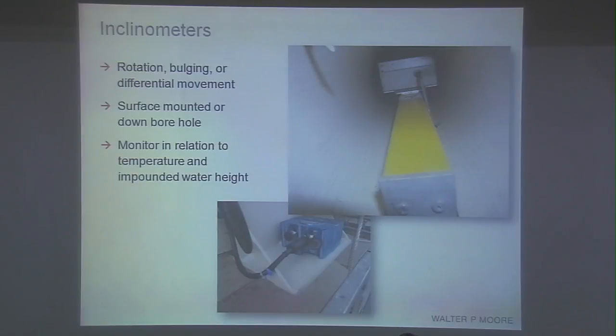Certainly, as some of the other presenters have mentioned, we want to measure all of the known factors which may influence the data, such as temperature and water height, and maybe some other parameters depending on the structure, because you want to be empowered to understand how these cyclical changes in the measured data relate to known phenomenon. So we know when we install these sensors that we will get seasonal variations or even daily variations with temperature. And so if we don't measure temperature, it's hard to make that correlation.